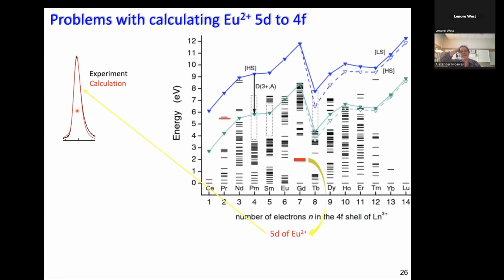This is an interesting aspect, and it always is surprising to me when you go to a conference about luminescence. There's, of course, a lot of different transitions. So let us look here. This is a table of the lanthanides. Unfortunately, I have only been able to track down one for lanthanide 3+. So that is why we are looking at europium 2+. And because this table or this graph that I found is for 3+, this is actually europium here then. Okay, so only one difference in Z.